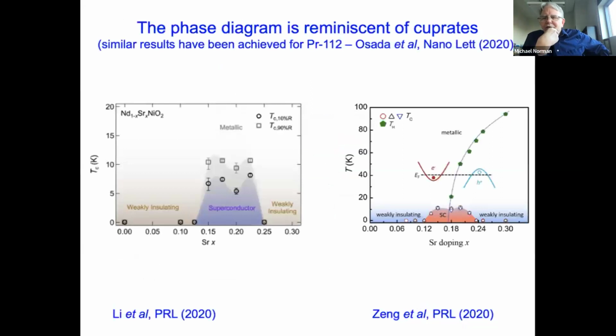And then when you map out the phase diagram, you get something somewhat similar to cuprates, roughly around 12% doping. You start, Tc turns on, and then it ends at 25% doping, which is exactly the doping level where superconductivity disappears and re-emerges. And you have sort of dips in the middle, what you think might actually be some sort of signature of charge ordering, like what happens in cuprates.